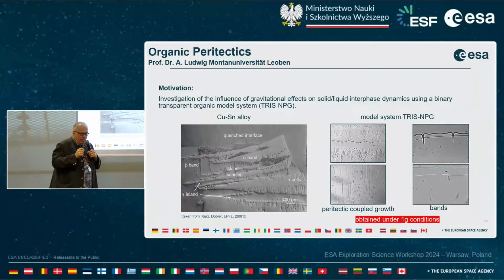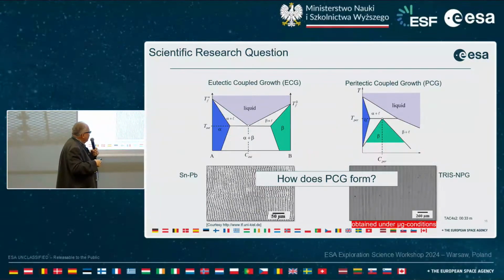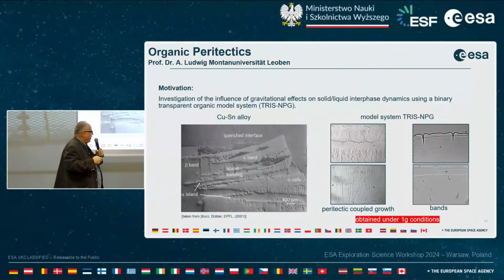So now coming to my work, and therefore I can go into a little more detail. Here again, you have this quenched material, and you can see we use, instead of a metal, an organic material to observe the dynamics. This is TRIS and NPG. So, same problem. Going back, you can see we found this even under 1G conditions. We found some bands here. This here is alpha and beta, here the same, and here we found something like eutectic growth, which occurs only if the solidification speed is very, very slow.